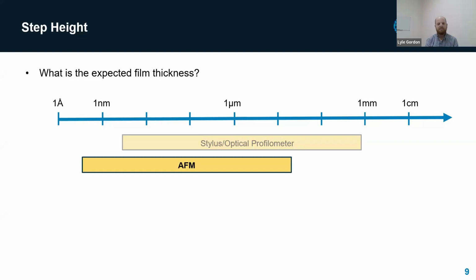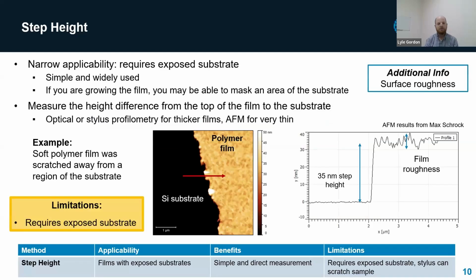substrate. So typically this can be done with a contact, like a stylus profilometer or an optical profilometer, or if you're looking at thinner films, an atomic force microscope is going to be useful. So we'll show a nice application using AFM for a thin polymer film. So in this case, a step height, basically what you're doing is measuring the height of the film relative to the substrate. So if the film is everywhere and you can't see the substrate, then you can't do this.